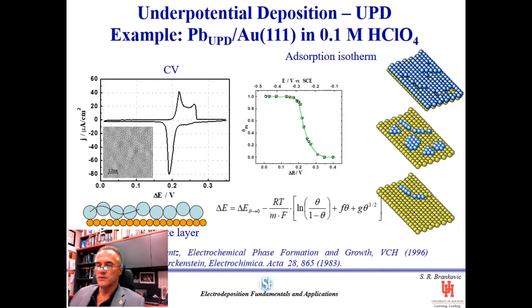Here I just want to give you an example of how the true voltammogram for UPD looks, on the example of lead UPD on gold, which is shown here. Here is the STM of the full lead UPD monolayer on gold, which exhibits a moiré type of structure due to the compression in the layer. Here you can see the adsorption isotherm, which is basically the lead UPD monolayer coverage with respect to the underpotential. And underpotential here is basically defined with respect to the reversible potential of the lead.